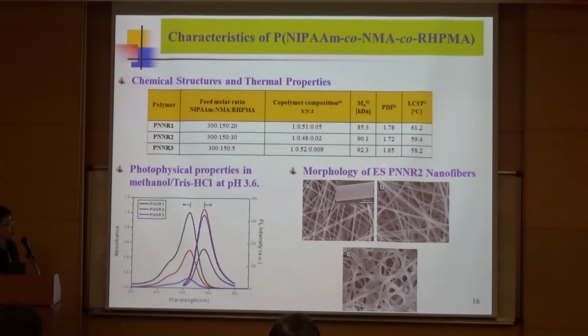The SEM images show the morphology of the nanofiber in different states when we use electrospinning to prepare the nanofiber. This is the as-spun nanofiber. The diameter was around 200 nanometers. After thermal cross-linking, there is no significant change in conformation. After immersion in aqueous solution, the nanofiber could maintain its fibrous conformation, with only a good swelling of water to a larger diameter, around 1 micron.